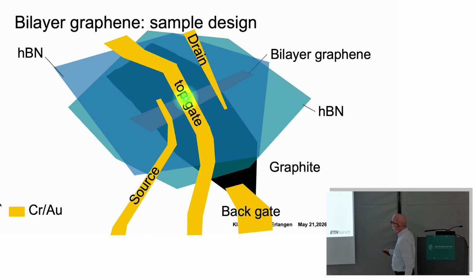So if you make a large band gap and the Fermi level is in the gap, then the resistance between source and drain should be infinite. It's like a switched off transistor. Actually, that's straightforward. The discovery of the band gap is now 15 years ago, but it took a long time to actually make a functional band gap so that you can have an infinite resistance.